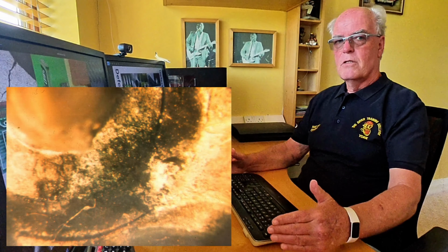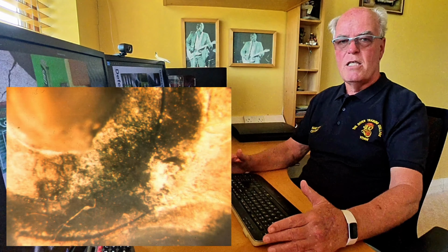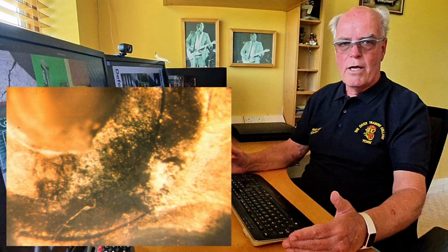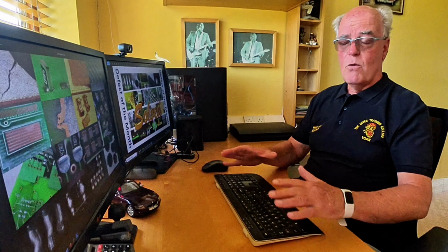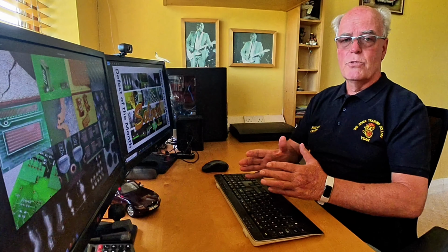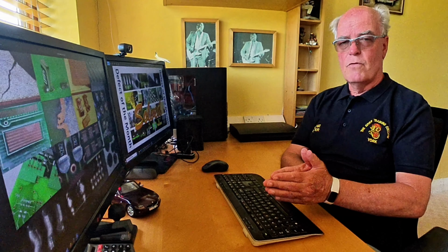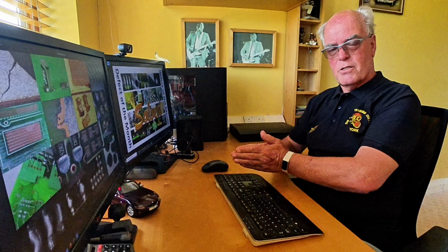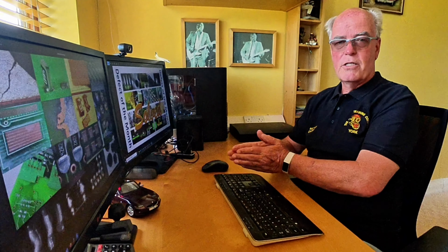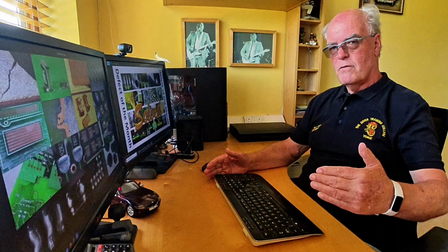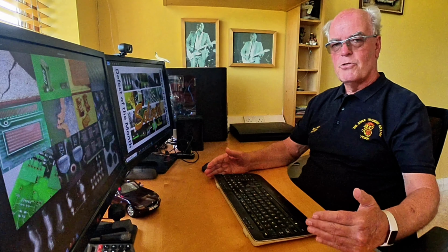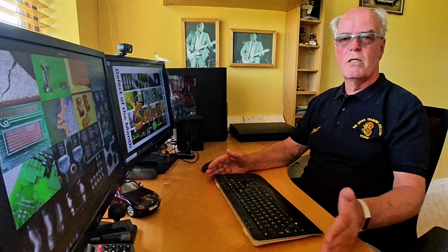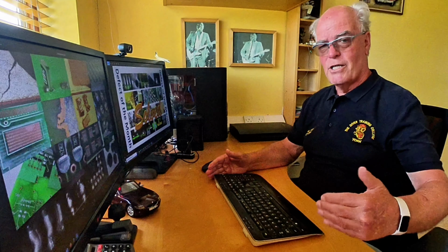Now I've removed that mask from the surface of the board, you can see the debris left behind. I had to demonstrate how this occurred, why it could have occurred, and how we could overcome it. So basically what I did is took a number of printed circuit boards. Some I soldered with water-soluble flux, some soldered with traditional low activity flux, and some samples that I didn't use flux at all. After testing in high temperature and high humidity with a voltage applied to the test circuits, we could see the difference between those three examples. So it proved what actually occurred.